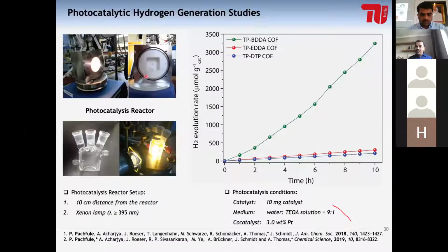And then in this particular reactor, where you can clearly see the magnetic needle, we had 10 milligram of the catalyst, 20 ml of the water and TEOA solution in 9:1 proportion. We had 3 weight % of platinum as a co-catalyst. And in this particular reaction, TEOA acts as a sacrificial electron donor, because we don't want to get the oxygen in there, because it is a 4 electron process, which is really hard to achieve. And we were just concentrating on the hydrogen generation rather than the oxygen part of this particular reaction.